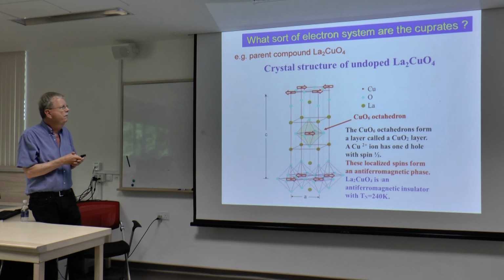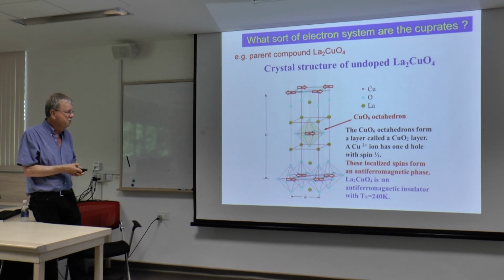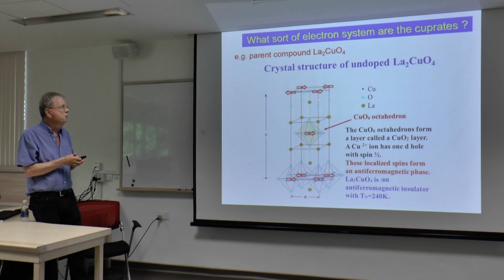and they order antiferromagnetically. If you don't dope it, it's an antiferromagnet. They order antiferromagnetically in their plane. There's the moment on the red dot at the middle, which you can barely see. Here's the moments on the red dots down in this layer. And then the oxygens are around the coppers.